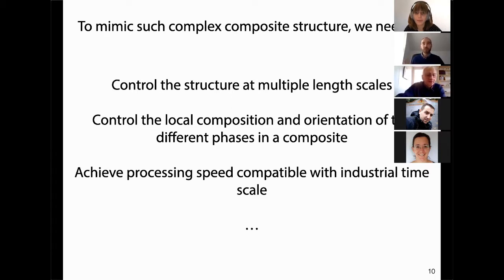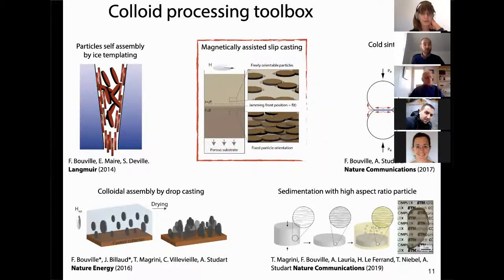And finally, we have an additional challenge, which is that we need to achieve processing speeds that are compatible with industrial timescales, because 100 micron of nacre will grow in more or less 3 to 4 months. So we can't wait. Even if we were able to reproduce the natural way of making this material, it would just be too slow. So we have to invent very much new processes to reproduce this structure and study their mechanical properties. And that's what we've been doing with the team at ETH, and now in London: pulling up a toolbox of colloidal processing to be able to reproduce this structure.